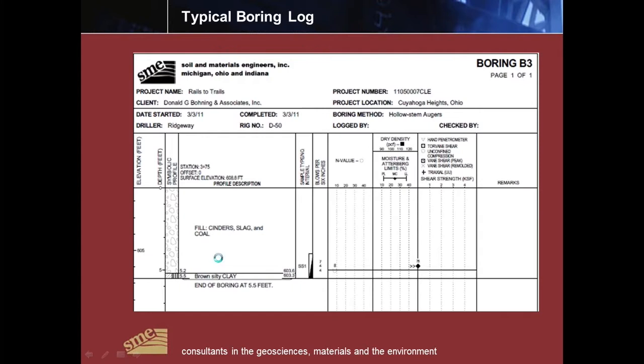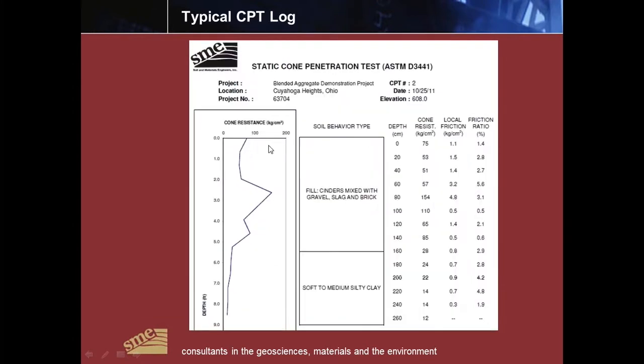Static cone tests revealed that we have an upper layer here, which is the fill, and it shows a nice granular crust by the cone resistance, followed by a weaker profile for the clay. Generally, when these cone resistance numbers are 20 or above, you would assign a basic bearing pressure of about 2,000 pounds per square foot for this material.